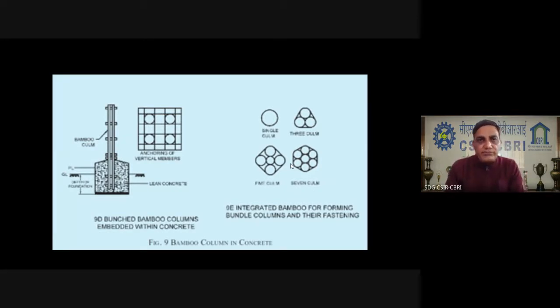When you are making use of bamboo as a structural element, particularly a vertical load carrying element, you can make use of a single bamboo if you have a reasonable diameter and good species. Otherwise, if your load requirement is higher, you can club the bamboo as one piece, or 3, or 5 or 7, the way you can see in this particular slide. That is the integrated bamboo forming a bundle of columns and their fastening. That depends upon how much axial or lateral load you are aiming for, and accordingly you have to combine or bunch the different diameters of bamboo together and connect them by means of bolt or pin connections, or by means of a steel or GI sheet.